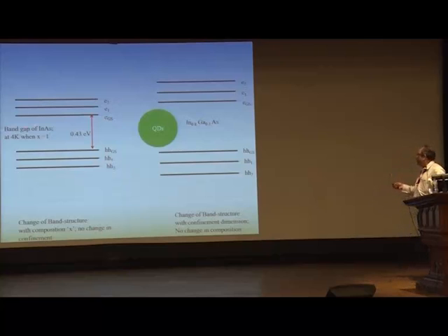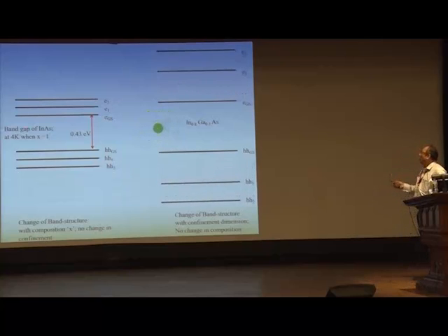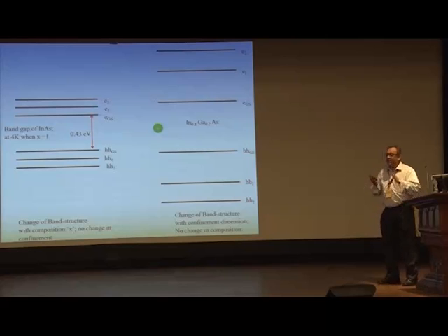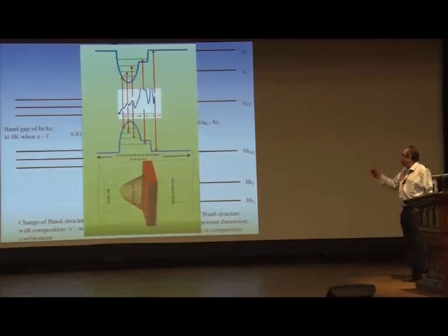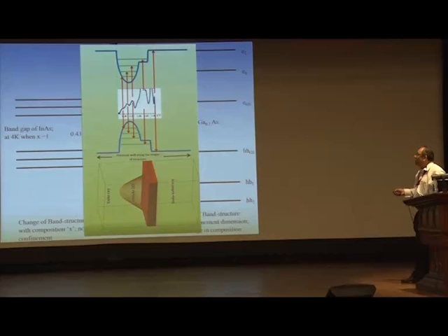You can also play with the size of the quantum dot. If you reduce the size of the quantum dot, the discrete levels get separated out. I have not shown the shape here, which goes into the scaling of the way these get separated. Now what is very trivial and simple and important is this diagram: the separation between the photoluminescence peaks is the separation between these jumps.